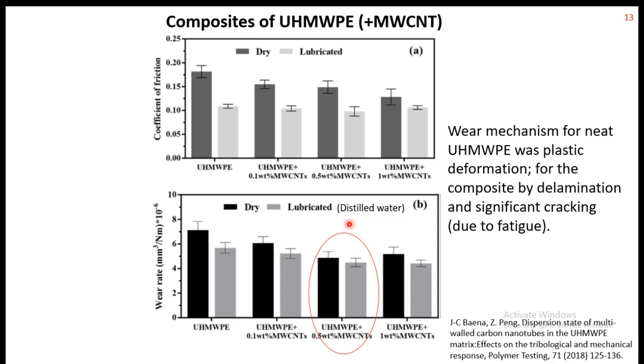Many times researchers use distilled water, but people also use bovine serum, which is closer to our actual synovial fluid. So the wear and friction behavior will depend upon what kind of material we use as a lubricant. Dry property will be quite different. We generally start with testing in the dry condition, and later move on to the lubricated condition, which is closer to the actual joint.